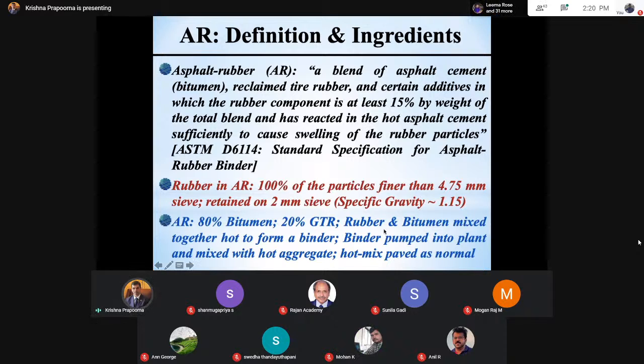So if you're blending rubber inclusions, I mean the rubber coming from discarded tires, when it is blended with asphalt cement, it is compatible. Why? Specific gravity is 1.15. I told you 1.01 for the binder, rubber is 1.15. They're not very far from each other. But this is slightly higher, which is why it can settle down. That's why the settlement issue is always there. So there is a handling issue and a settlement issue within the asphalt storage tank. These two are very important problems that are prevalent, where we are not very successful in the country.